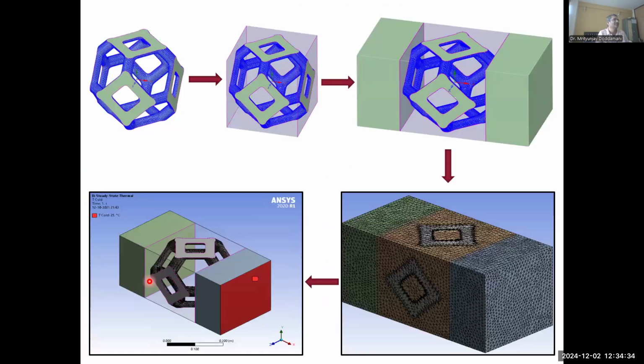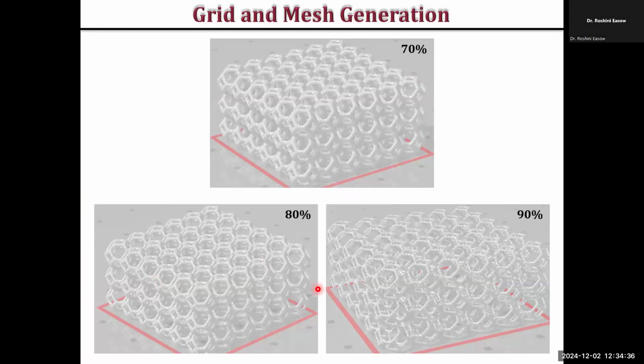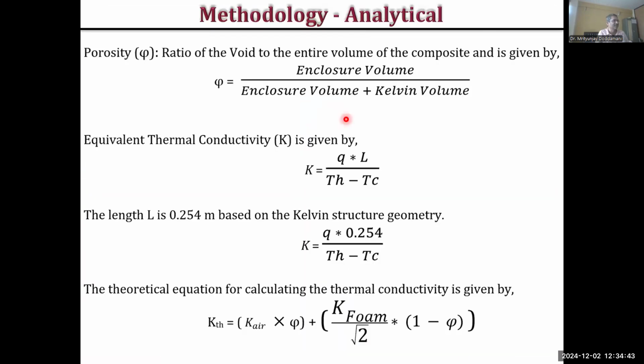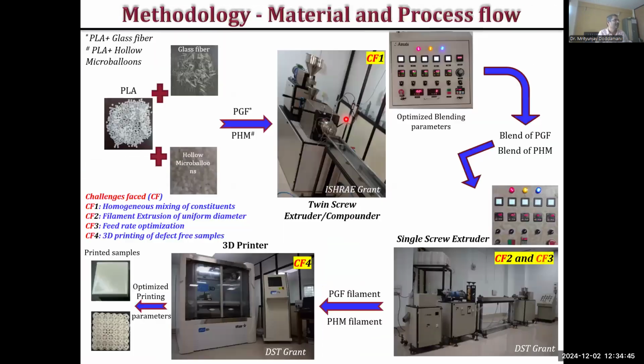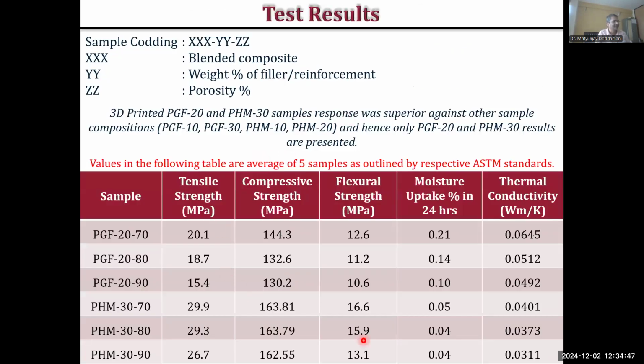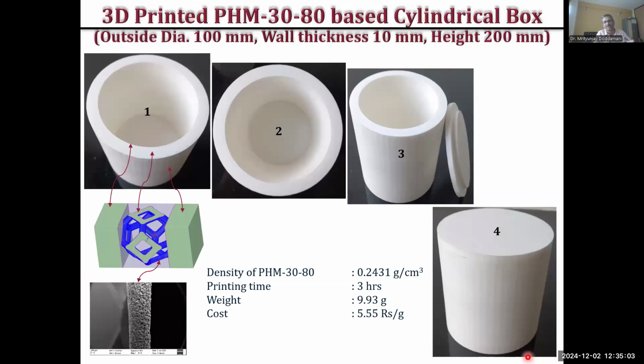I think I have already shown it here. Here now the struts are made up of that material with that much additives, but with a different porosity level. So with this, we were able to reach 0.0311 experimentally. So we were very close to our CFD simulation and analytical investigations. So we went ahead with this just for an example's sake, because ultimately the product should come out at the end after doing all this.